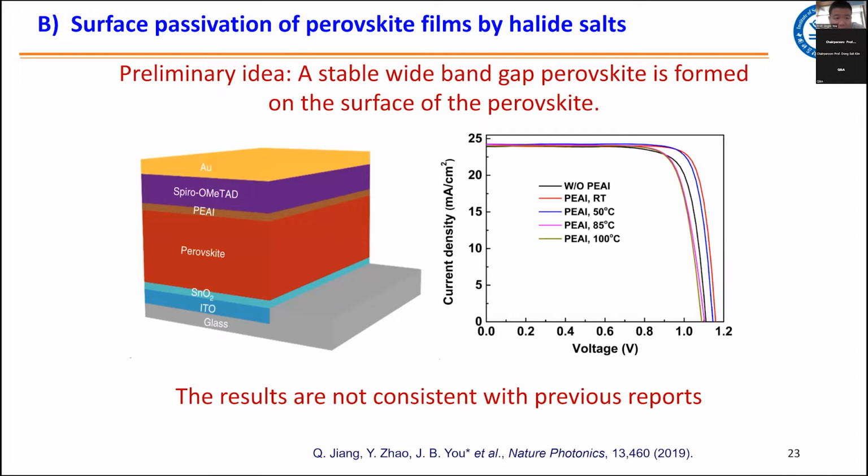The second one is passivation. People have found that the organic iodide can passivate the grain boundaries or the bulk. However, there are still a lot of defects on the surface, because when we heat the perovskite materials or precursors, some elements or ions may evaporate and lead to point defects. The defects are mainly iodide vacancies. So how can we try to avoid the surface recombination?